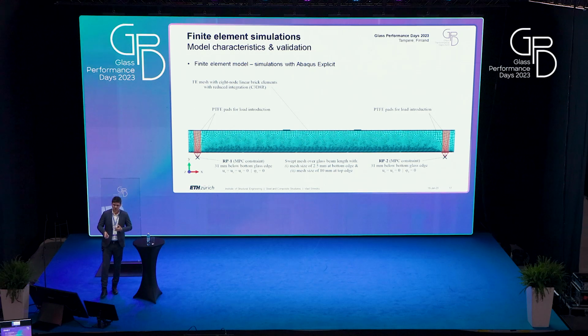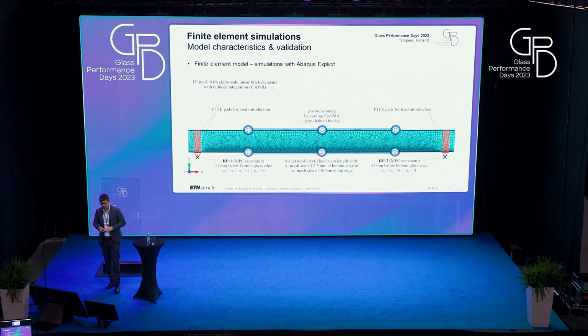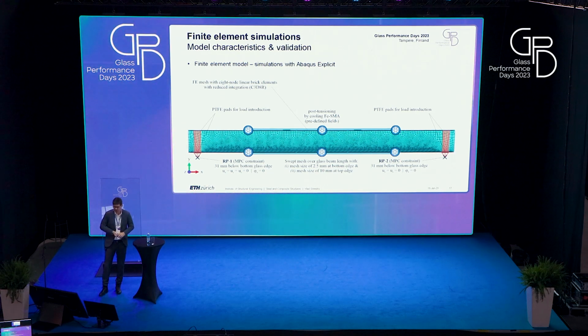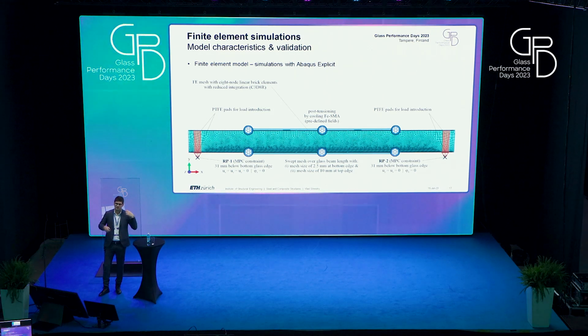For the activation part, we assumed cooling along the middle parts of the strips with predefined fields in Abaqus, and we calibrated the cooling temperature to reach the same strains in the system as we measured in the experiments I presented before.